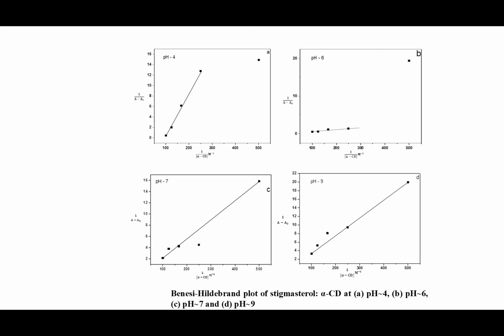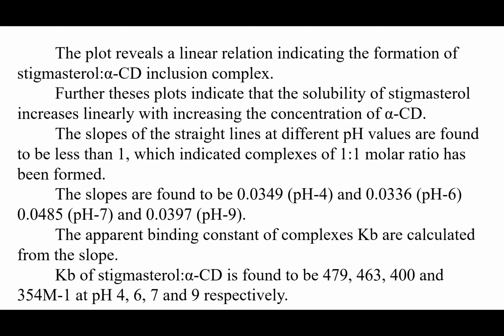And here's another important piece of information: when the slopes are found below 1, it indicates the stoichiometry ratio between the alpha CD and stigmasterol is 1:1. So here also we have calculated the binding constant. And for stigmasterol alpha CD complexes, the binding constant values are obtained as 479, 463, 400 and 354 M^-1 for different pH values.